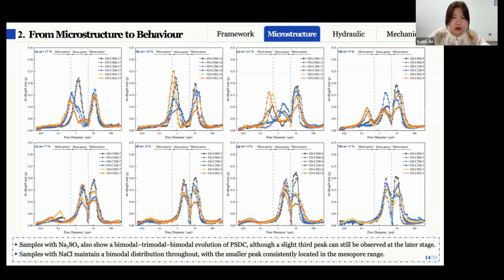In contrast, for the sodium chloride C2 samples, the PSD remains bimodal along the drying, and the smaller peak stays within the mesopore range. This can be attributed to the double layer compression effect of sodium chloride. It stabilizes the pore structure and limits its evolution. So if we take C0 S0 as a reference, sodium sulfate S2 shows a similar evolution pattern, suggesting a relatively limited effect on the overall microstructure. But if we instead consider the initial structure as a reference, that is, C0 S0 compared to C0 S0, C2 compared to C2, and S2 compared to S2, we can see that sodium chloride maintains a stable bimodal distribution, indicating a more stable pore adjustment process.